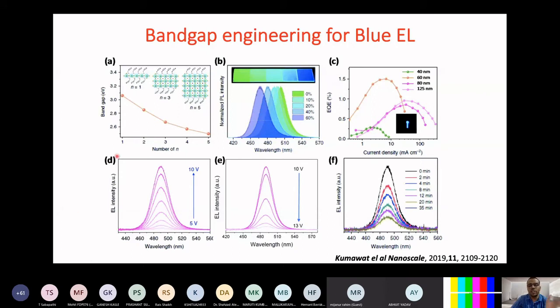So instead of going from iodine to bromine and bromine to chlorine to do the band gap engineering, there's another way you can do band gap engineering. You have the same bromine-based structure, but now you can make them n equal to 1 layer, n equal to 2 layer, n equal to 3 layer, and that allows you to do band gap tuning again, and you can get the color according to your choice.